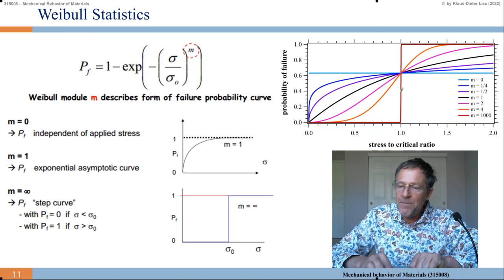So the m describes somehow the width, like the full width half maximum. If it goes from here to here, then this is the width. From one level, let's say below 0.2 and above 0.8, so you exclude that, and you look at the width in the stress range. So you see already it's something like 1 over m, the width. And as m becomes larger, the width becomes smaller. We're not looking too much into exponents smaller than 1.